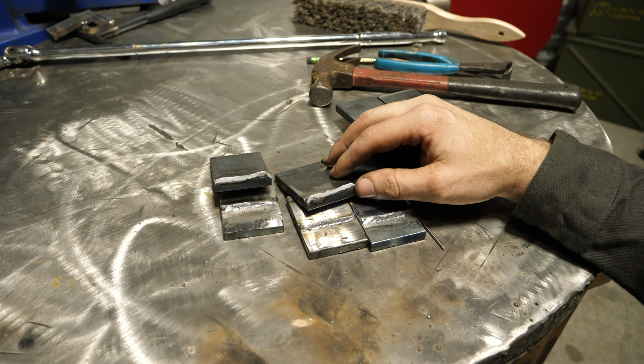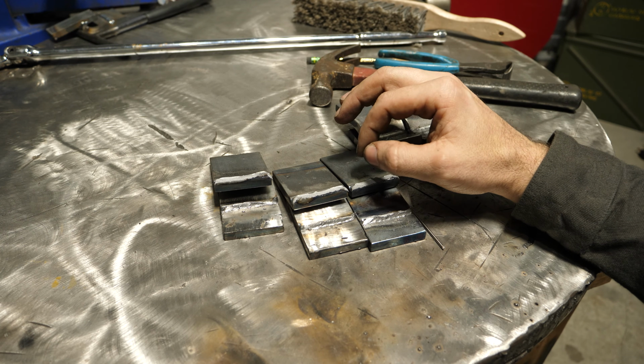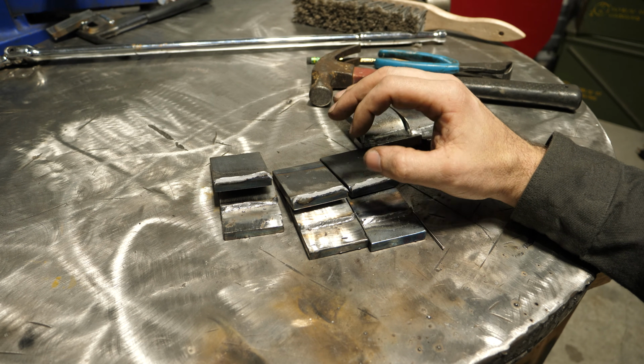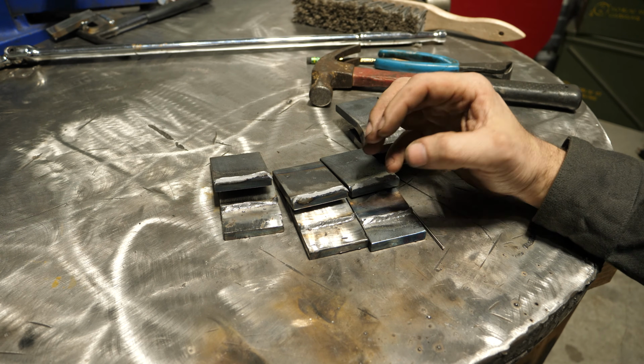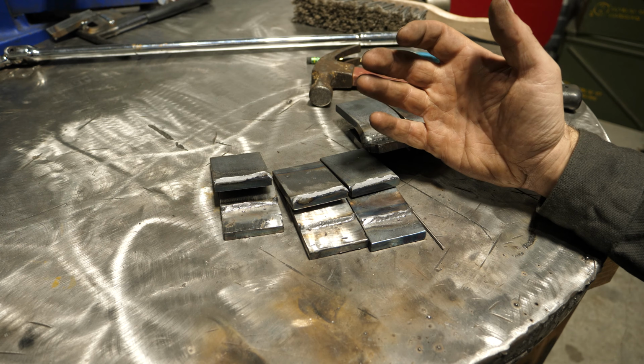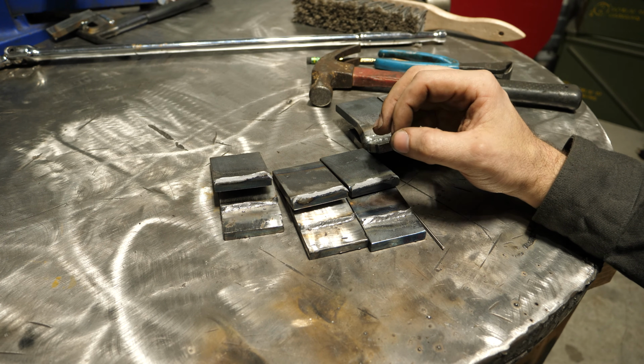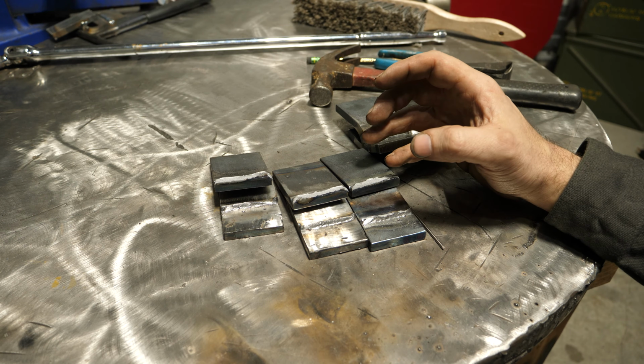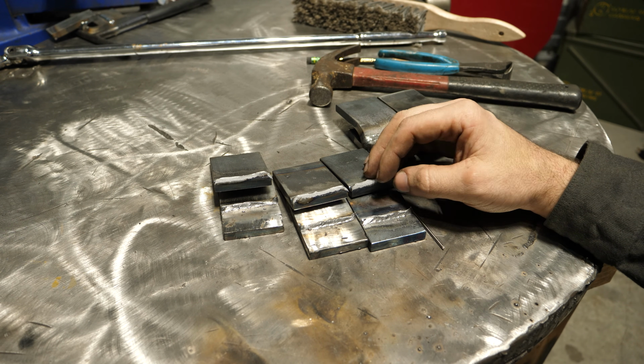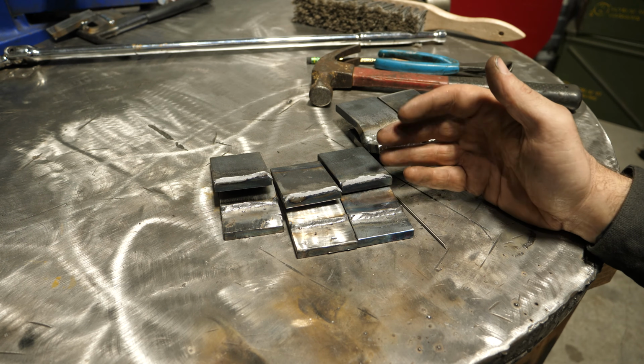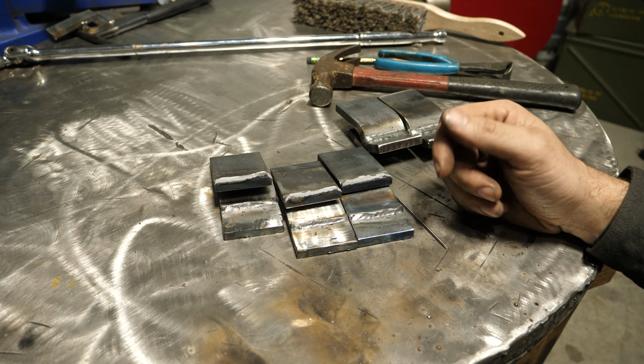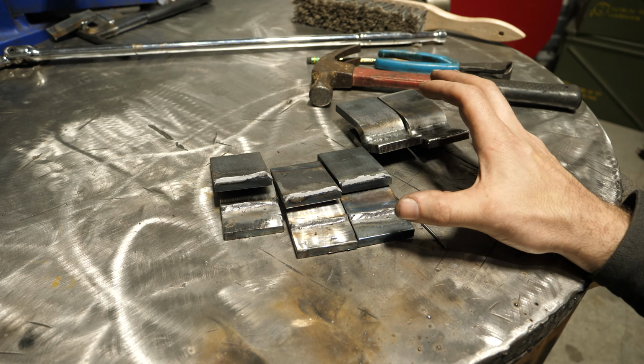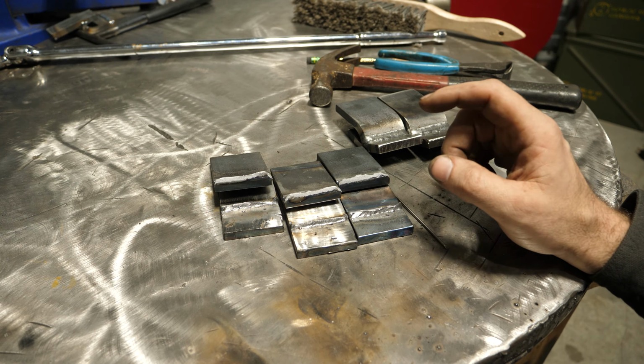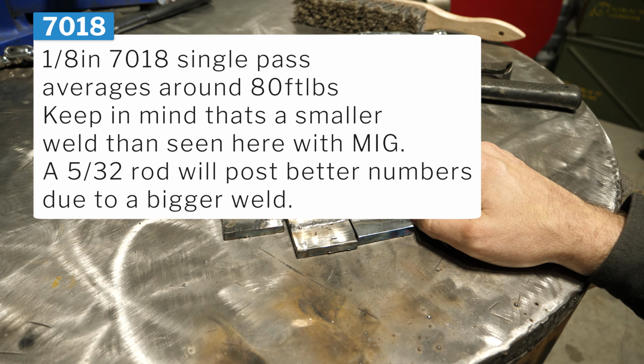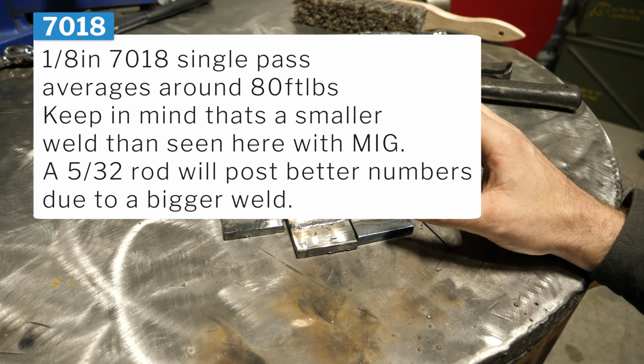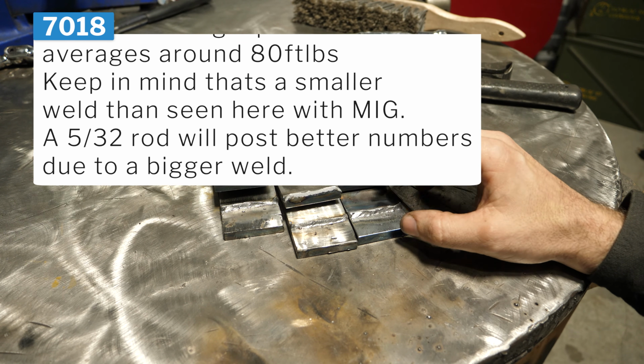And that's part of the reason why TIG produces such strong welds, is not so much that the wire or the process is stronger than, say, short arc MIG or stick, it's just because the process is so prone to having clean welds without defects, such as lack of fusion at the start, that the overall consistency weld to weld is better. And again, I will say I'm pretty impressed that 200 amps on MIG with C25 gas was able to do what it has done here. It has actually exceeded the strength of 1/8 inch 7018 in my testing, which again, has to do with a bigger weld size, but still, this is better than I would have thought.